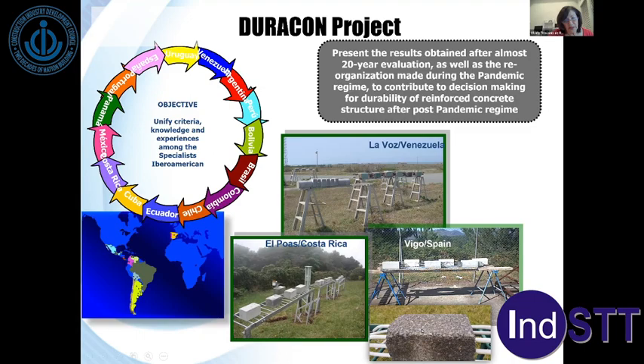Two different mixtures were prepared, with water-cement ratios of 0.65 and 0.45. Six concrete prisms of each concrete mixture were placed in each exposure site. Three were plain concrete, non-reinforced prisms, and the remaining three were reinforced with rebar.